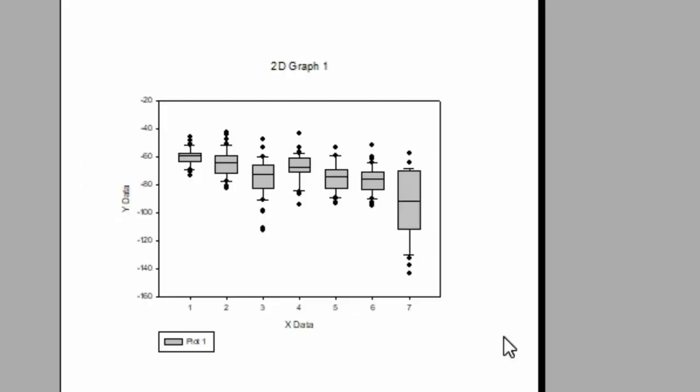Again, still, the lower the number, the stronger the material is. And group one, I did not cure at all. Group number two, I cured for five minutes. And number three, I cured with 10 minutes and so on and so forth. You can see the longer I cure it, the stronger it gets. Maybe the bigger the variance it will be. It's weird. I have another study coming up to try to figure out what those variants come from. Maybe it's because of the position on the curing machine or something else not worth investigating.